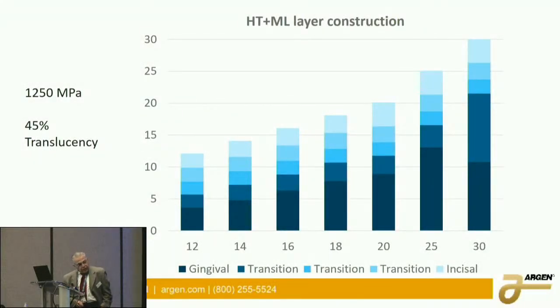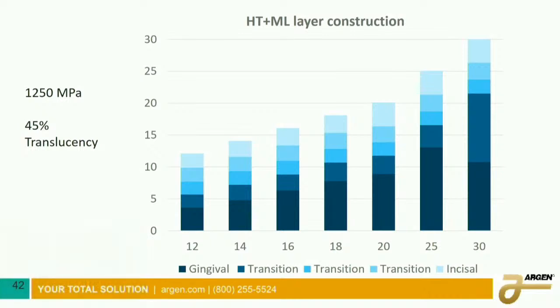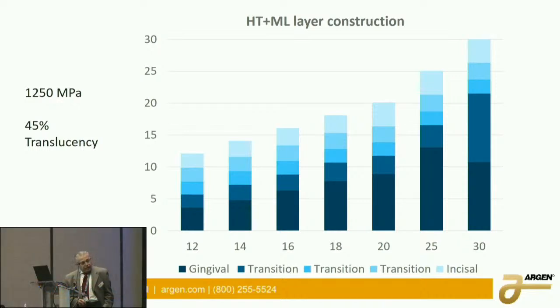As the size of the disc increases, the transition layers also will be modified. The incisal layer gets modified. You see here we have a much larger incisal layer than we do on the 12, on the 30. And we also make 30s. Some companies don't make them that large. And the transition layers also get modified. And we take into consideration those natural curves that are in natural dentition. And our materials wind up to be a little easier to nest. And again, you have a high strength level throughout the entire restoration, and as well a higher translucency.